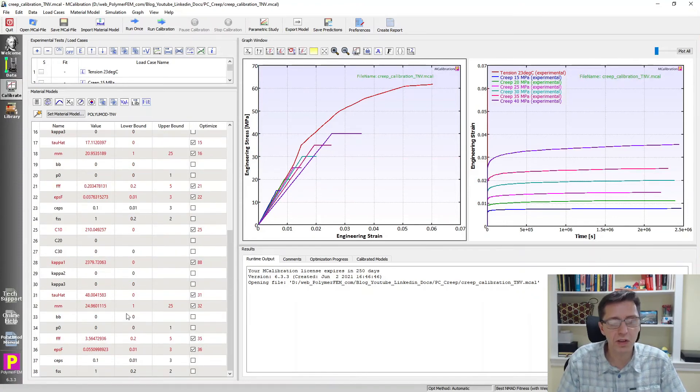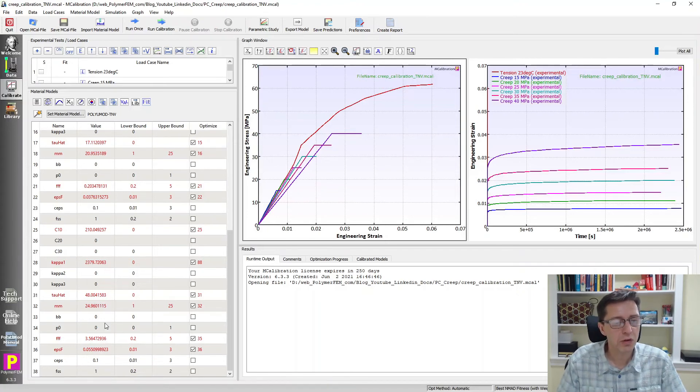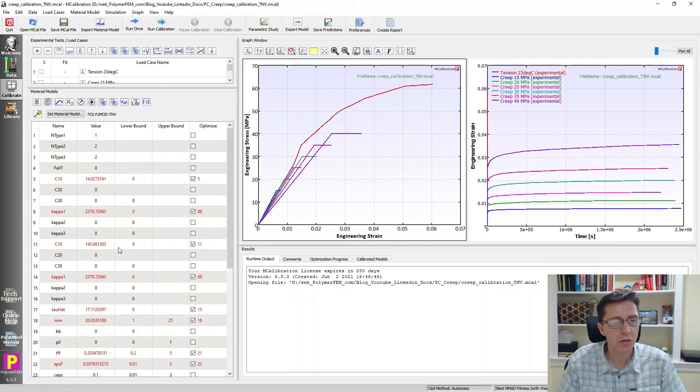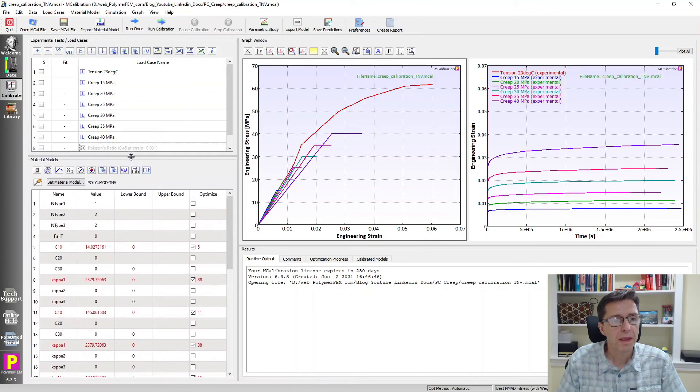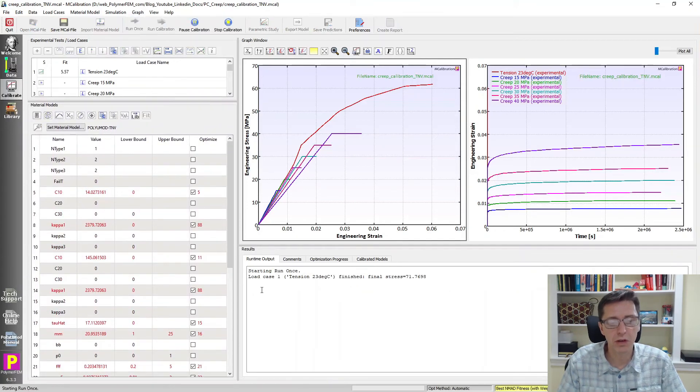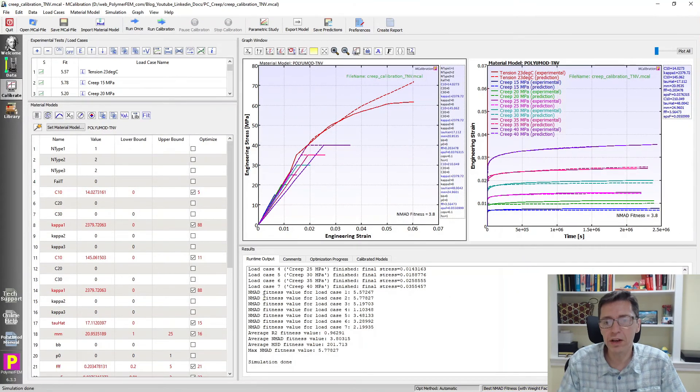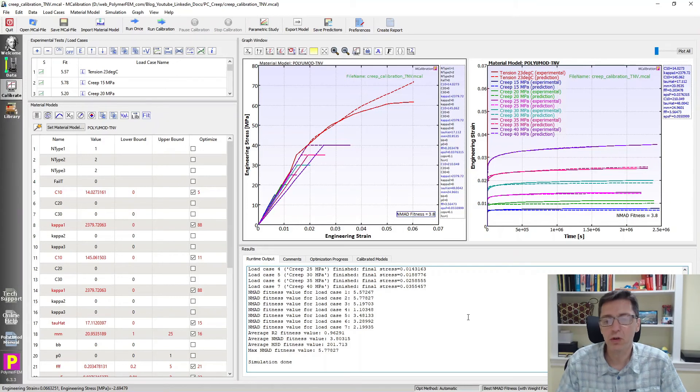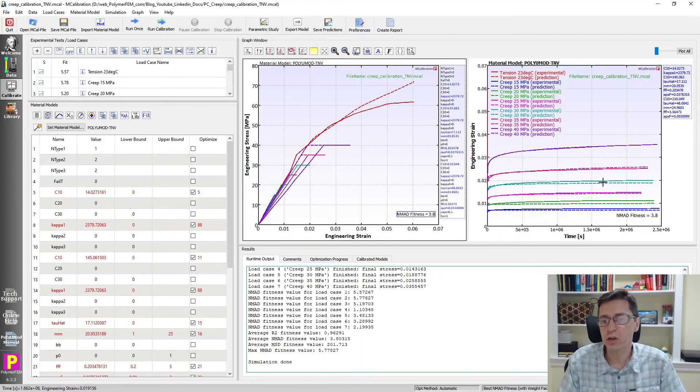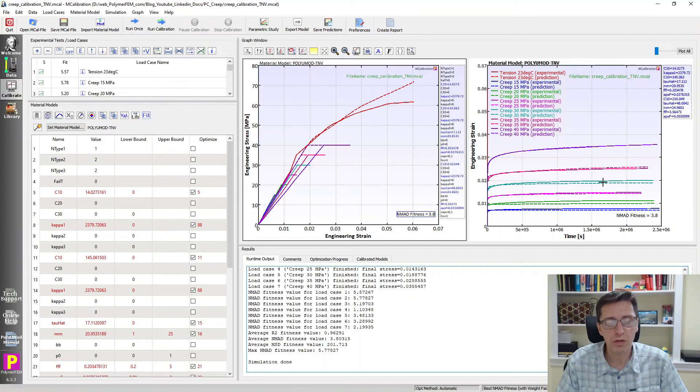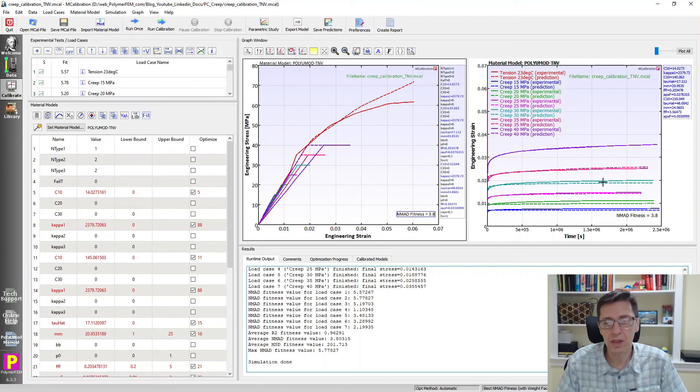That's where I set up here. And if I run this once, it's a nonlinear viscoplastic material model and the error is about 3.8%. So it's about half the error of any of the other models that I showed. Particularly interesting is the figure to the right showing the creep predictions are actually quite good for all stress levels. This will be the most accurate of the models that I talked about so far. This is my recommended model for this material. It is more accurate than the other ones.